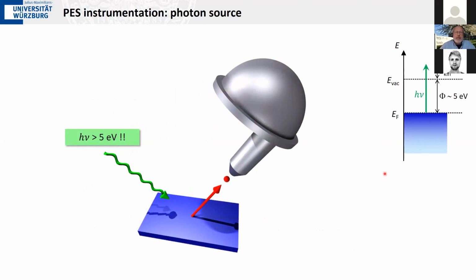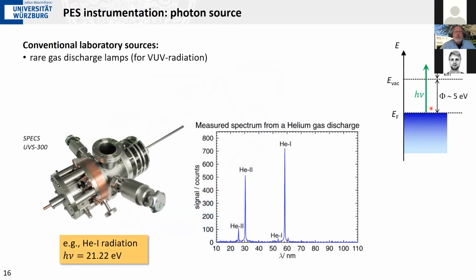You need something that produces photon energies high enough to overcome the work function. Typical work function for a solid is somewhere between 3 and 6 electron volts. So you want to have photons that have 5 electron volts or more in order to excite photoelectrons. And one particular important source that we use in the laboratories is a helium lamp.